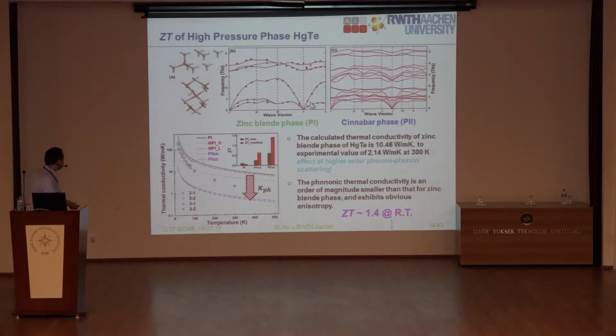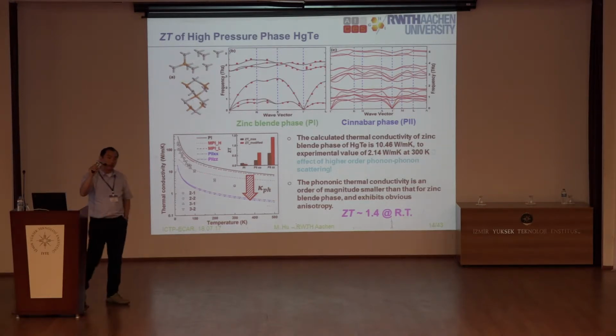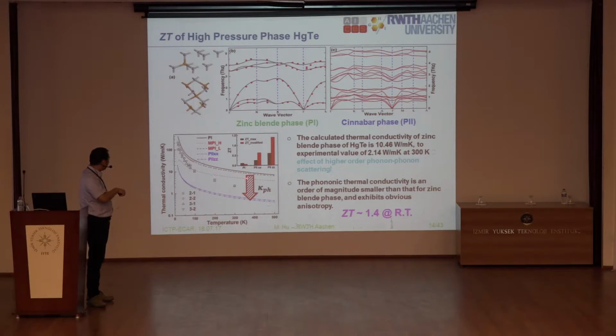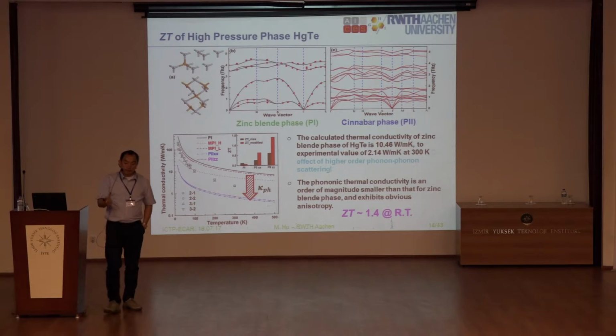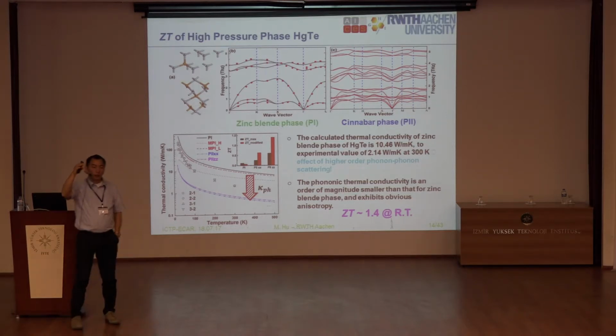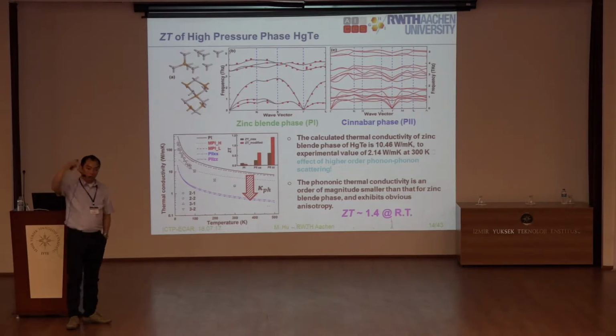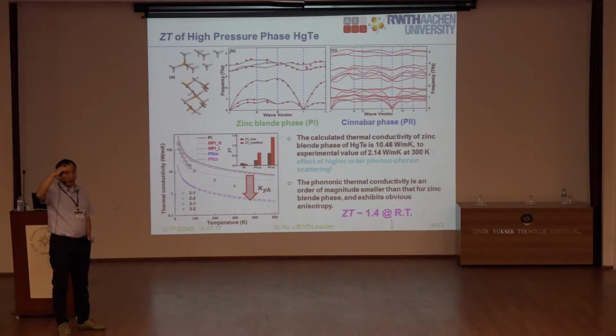Just the previous page. Yeah, the dots are an experiment, and this is our numerical simulation. This is after we consider the defects in the material, and you can still find that you have some discrepancy. The BTE will give you a higher thermal conductivity evaluation, and right now we realize that there could be a higher order phonon scattering contribution. Because in this BTE calculation, we didn't consider the higher order, that's why it's higher.